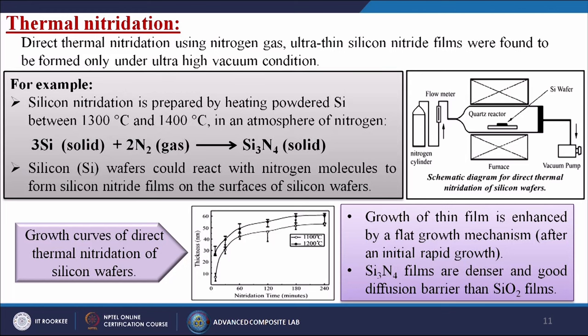Here is the schematic diagram of direct thermal nitridation of silicon wafers. We have the nitrogen cylinder, then a flow meter by which we can control the flow of nitrogen inside the chamber. Then we have the silicon wafer; the nitrogen goes into the quartz reactor, and we connect it to a vacuum pump so that the inside is under vacuum. Then we put the whole reactor into the furnace so that we can increase or decrease the heat on the substrate. Then the nitrogen reacts with the surface and forms silicon nitride.